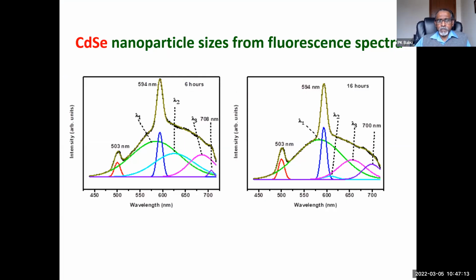excite these glasses. This is a typical glass containing cadmium selenide nanoparticles. Along with the emission of the lanthanide ions, we have seen that even the nanoparticles of the semiconductors or the metal ingredients that we have embedded, they also emit light when we excite the atoms using an external laser. So here you can see that along with the emission, the narrow peaks that you have, these are the emissions from the lanthanide ion. The broad spectrum that we have is due to the emission from the cadmium nanoparticles. You can see that even those emissions vary depending upon the duration of the annealing, because the sizes of the nanoparticles have changed.